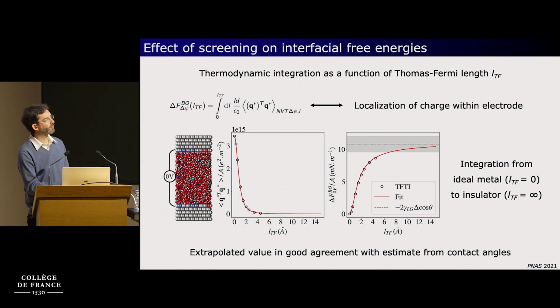But the important thing is that when you go from LTF equals 0, which corresponds to the perfect metal, to LTF equals infinity, which corresponds to the insulator case, we obtain an extrapolated value which is consistent with what we estimate from the contact angles, which is the dashed line here with the error bars as a shaded area.